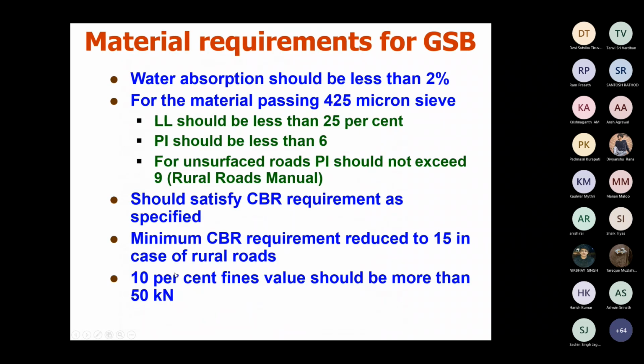Now the requirements of the materials for granular subbases: the water absorption should not be more than 2%, and for the material passing the 425 micron sieve, make sure that the liquid limit value is less than 25% and the plasticity index value is less than 6%.